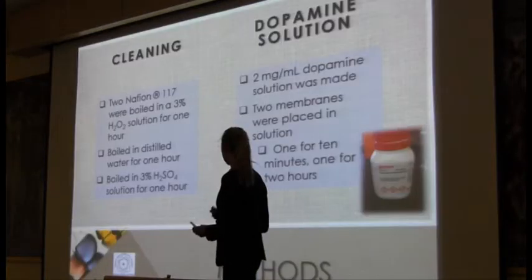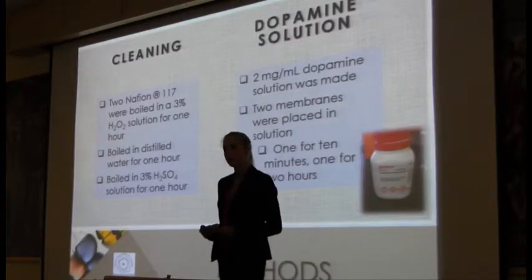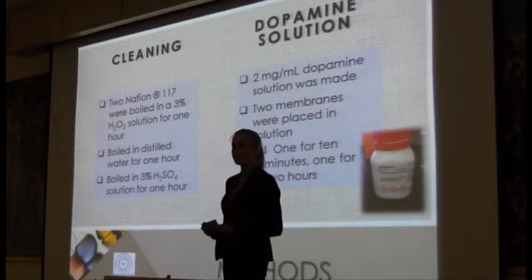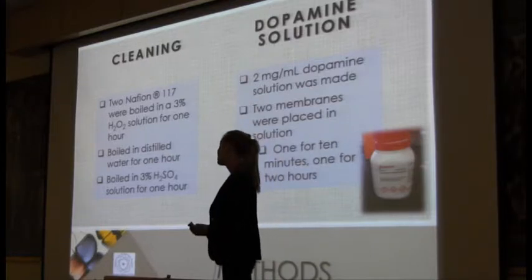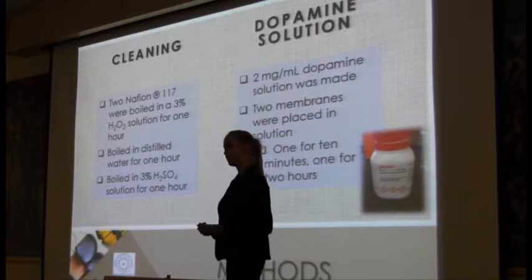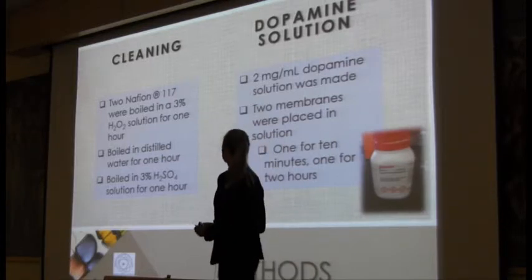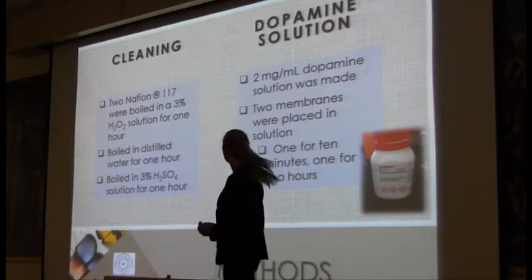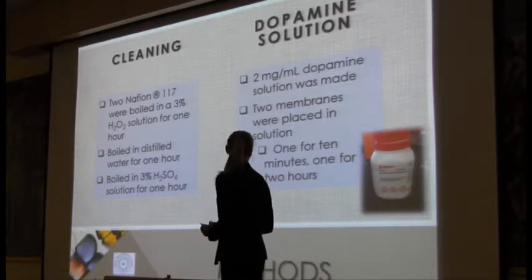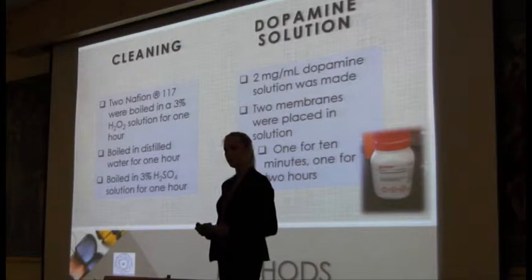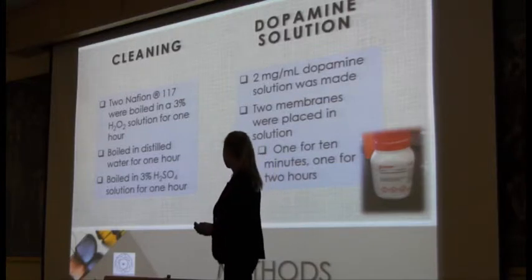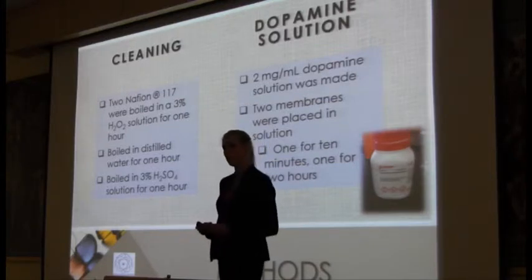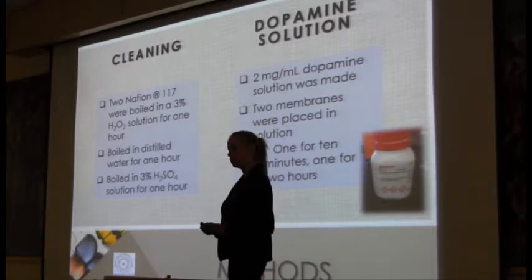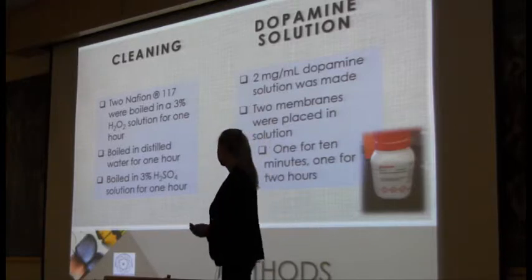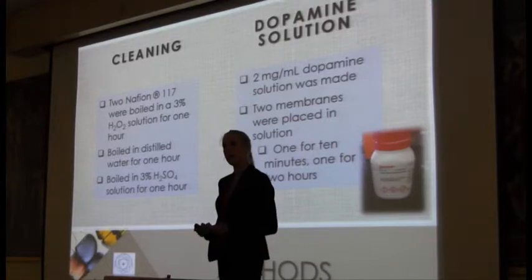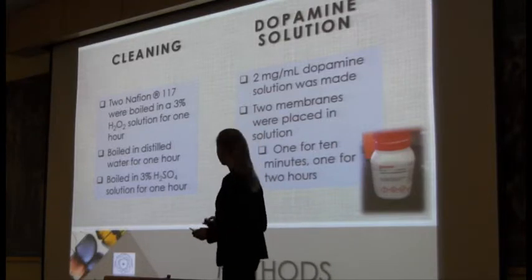So to begin this experiment, we cleaned 2 Nafion-117 membranes by boiling them for 1 hour in a hydrogen peroxide solution, 1 hour in distilled water, and 1 hour in a sulfuric acid solution. To create the dopamine solution, we made a 2 milligram per milliliter dopamine solution with dopamine, Tris buffer, and distilled water. We stirred it and it turned a slight brownish color. Then we immersed the membranes in the solution. One membrane was immersed for 10 minutes, the other for 2 hours. Once the immersion time was complete, we took them out, rinsed them with distilled water, and placed them in distilled water until further use.